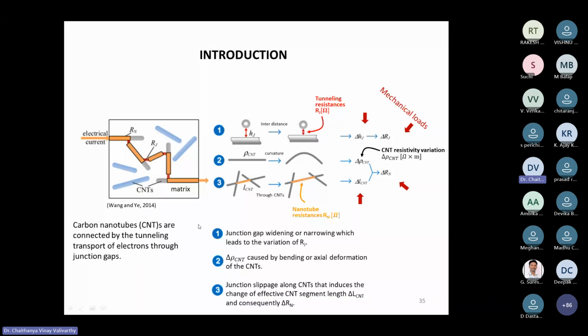piezoresistive whole composite. So the first thing to achieve this piezoresistivity property is junction gap widening or narrowing, which leads to variation of resistance. Then change in curvature, change in resistivity caused by bending or axial deformation of the CNTs. The third one is junction slippage, which induces the change of effective CNT segment length, delta L, and delta R is the change in resistance. So using these three phenomena, we can get the piezoresistivity of a composite inside the matrix.